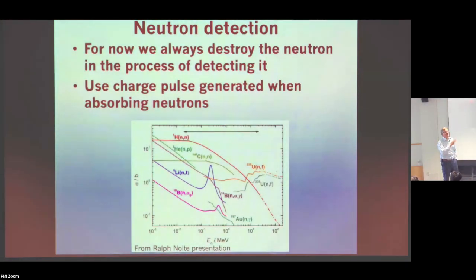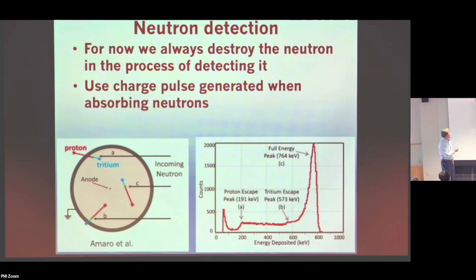Okay, so then in terms of the neutron detection, that all has to do with destroying the neutron, which is actually unfortunate, but we don't really have a way around that for now. So typically we'll use a material that absorbs neutrons, and almost entirely we're using helium-3 as a gas. We use a linear proportional counter, creating a proton and tritium in the process, and then detecting the charge shower that comes from that. This is what the detector looks like. There's an anode, cathode, neutron comes in, creates a proton and a tritium ion, and those get converted by amplification through the gas itself, ionization of this gas. Then there's a charge pulse arriving at the anode, which is amplified and creates this type of spectrum.